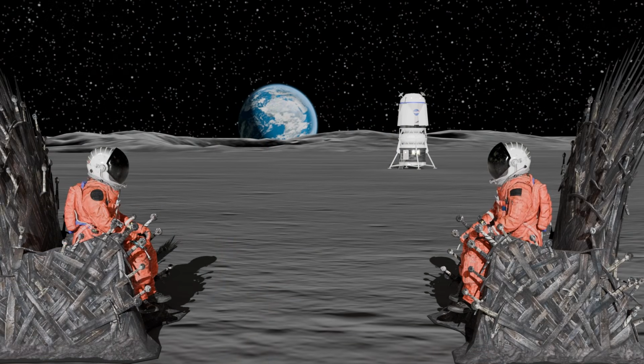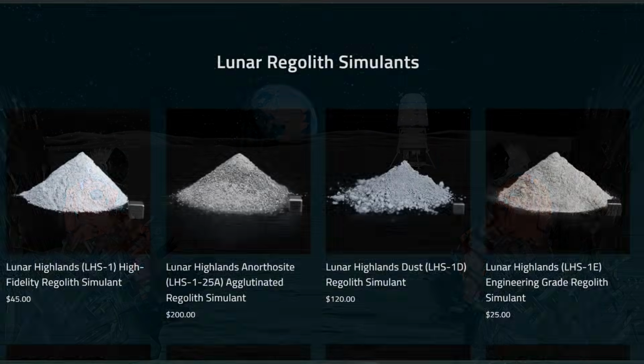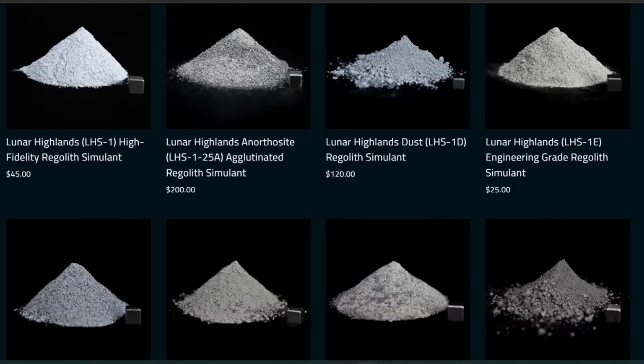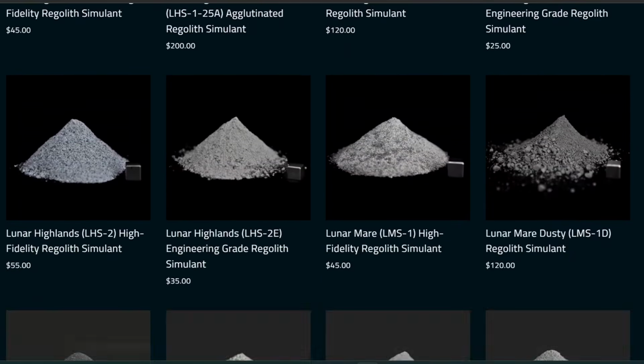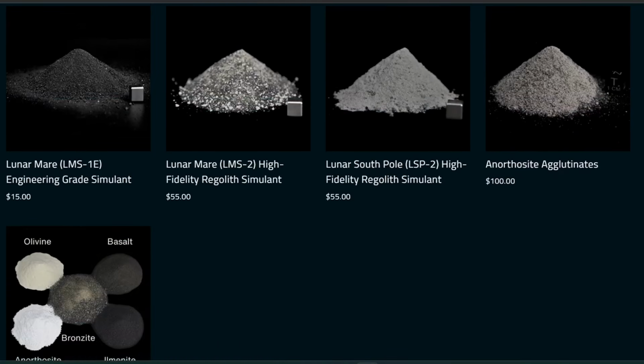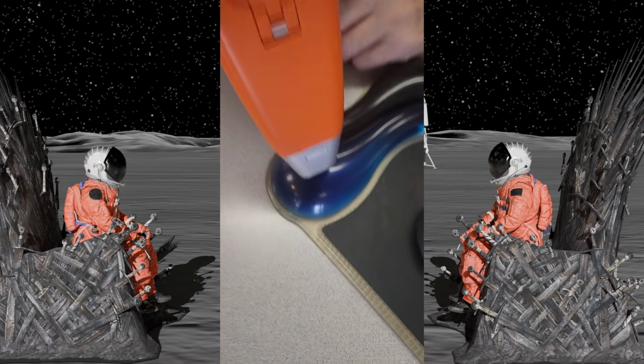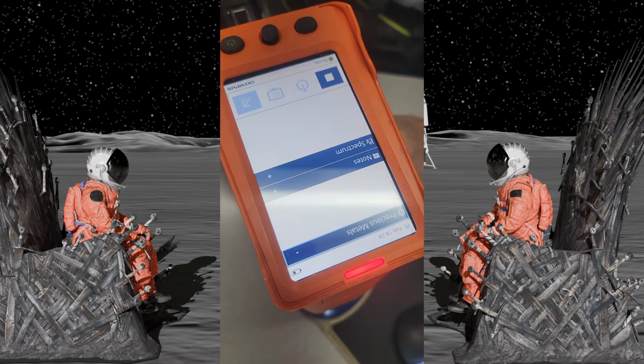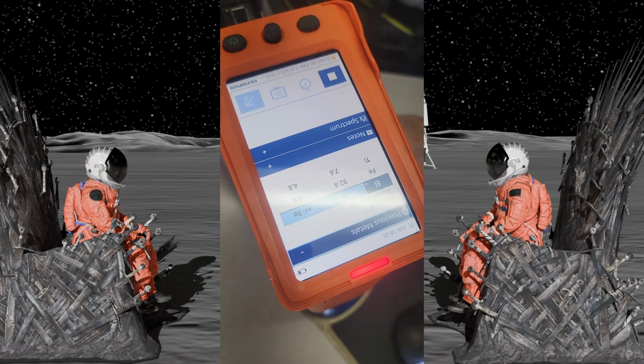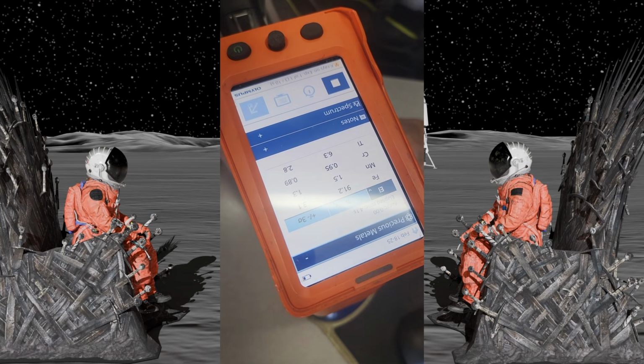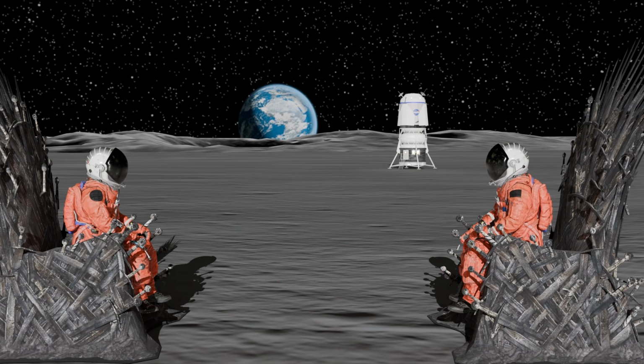So the first thing we needed to do was create a simulant to work with. And since we were doing a lot of experiments, we needed a lot of it. But simulant is quite expensive, like $50 a kilogram, which if you're a government-funded lab with deep pockets is no big deal. But we're sort of the furthest thing from that here. I mean, this is garage science. So what we did instead was we used XRF data from Apollo to make our own simulant. And we also bought 1 kilogram from a distributor to make sure ours was as good as professional grade simulant sold commercially. And in some ways, I suspected ours may have actually turned out a bit better, like with titanium contamination, but I'm getting ahead of myself here, and I'll let you talk about that later.